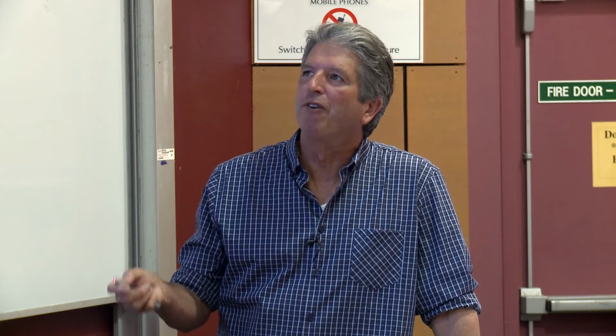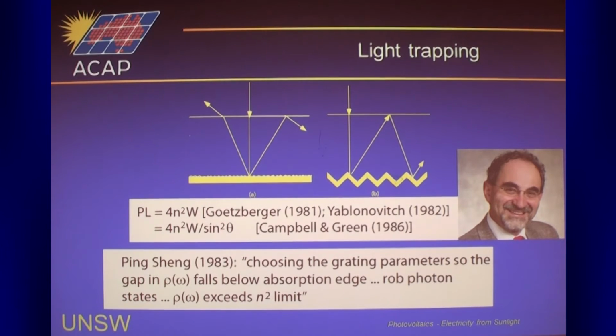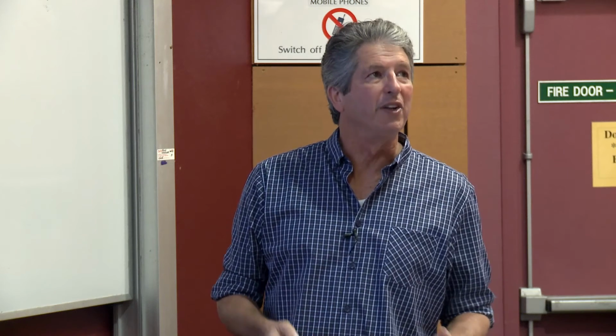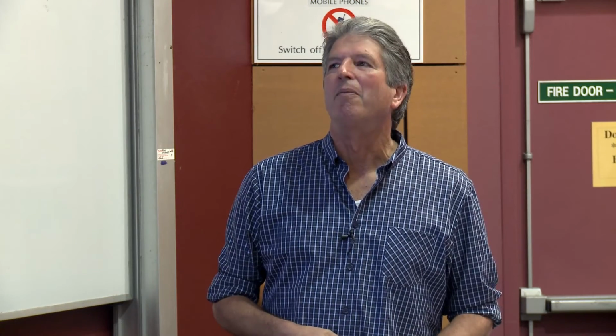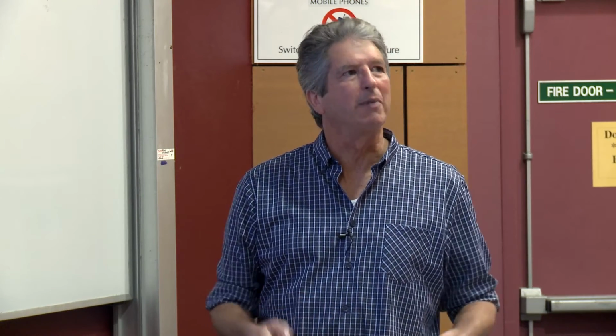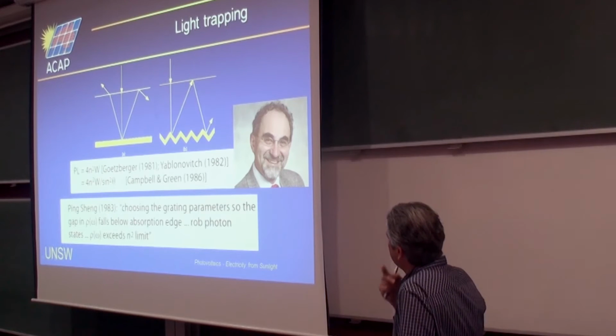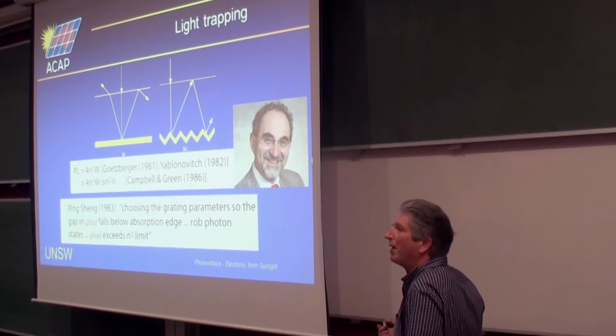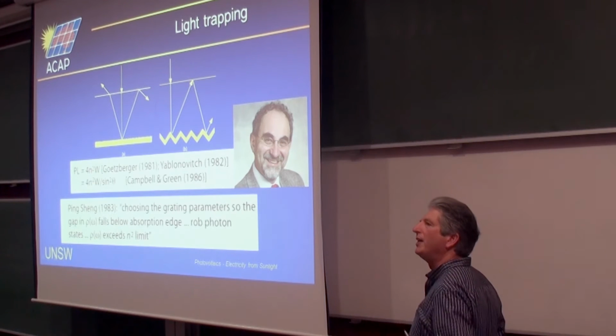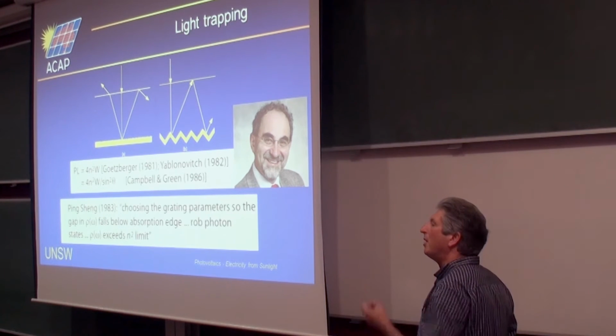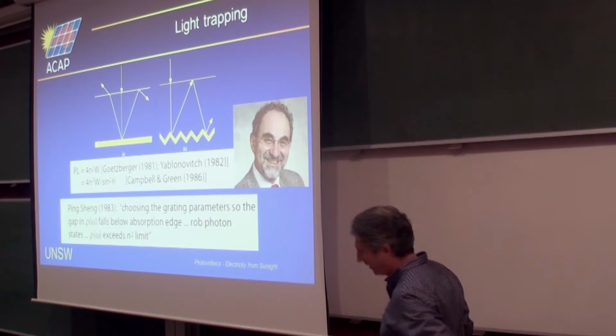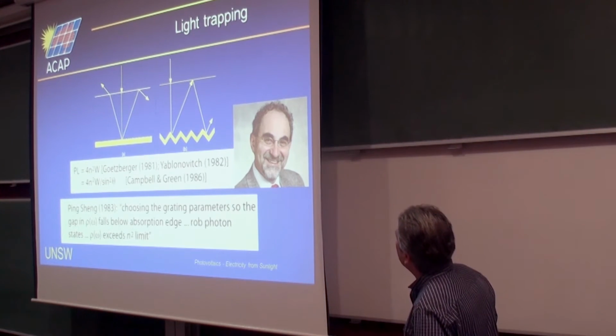I might add these are all for very thick cells, much thicker than a wavelength, and there's been a lot of recent work on what happens when the cell thickness is small compared to a wavelength. Can you get enhancements beyond this? And the answer is not in the average case, but in some extreme cases, yes, very, very much so. So that's what's meant by light trapping, and it's a function of the high index of silicon. So we started to think about incorporating that into our designs around this stage.